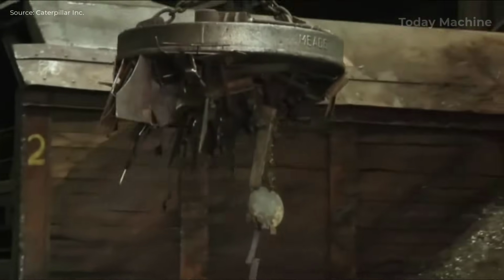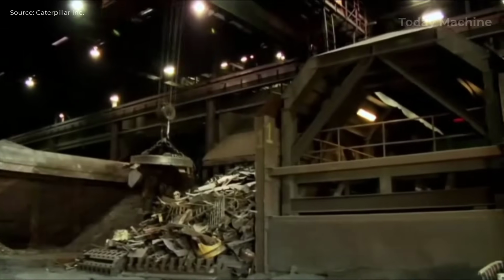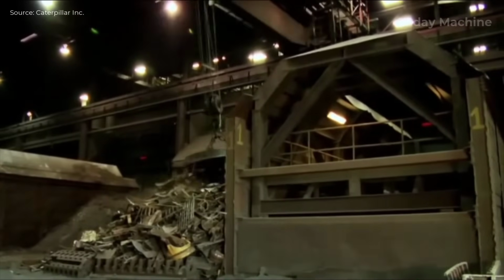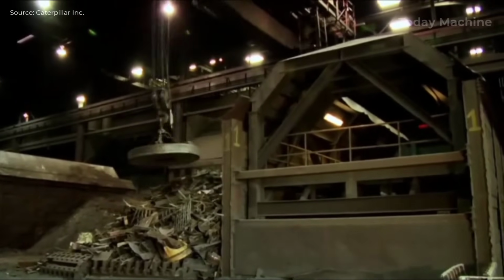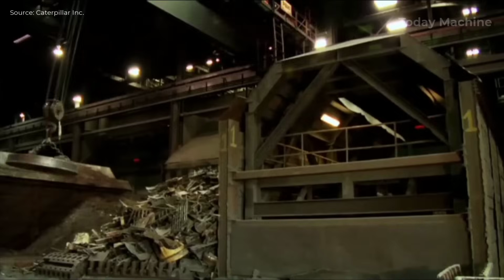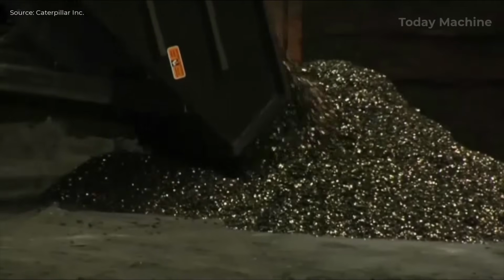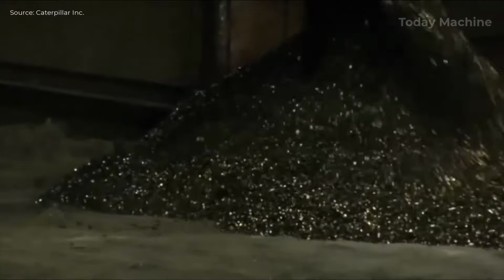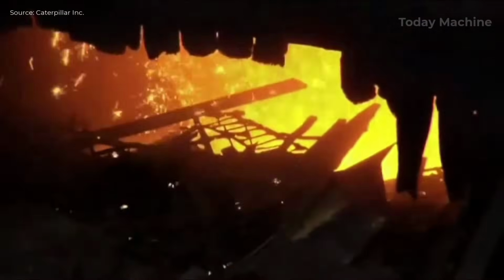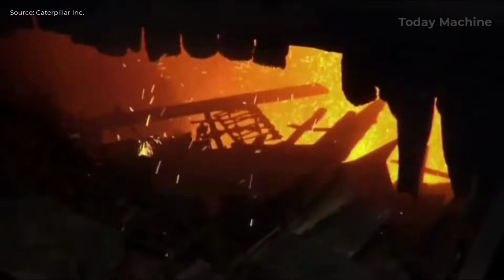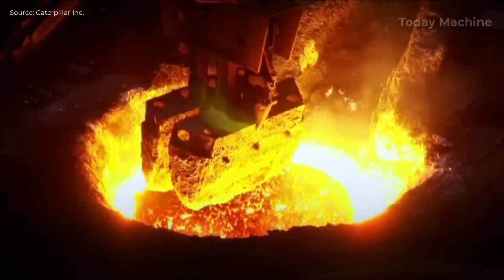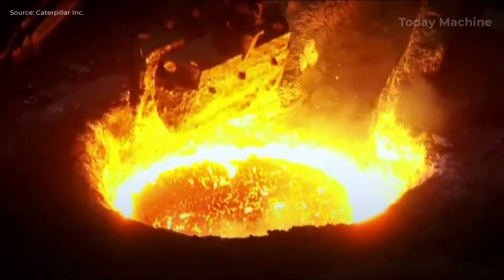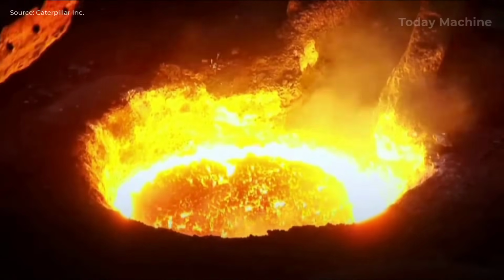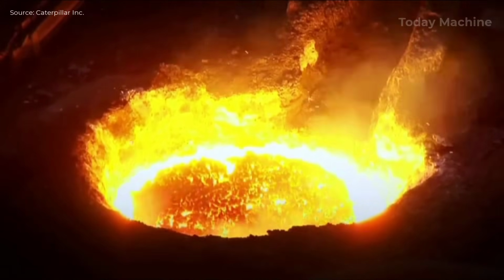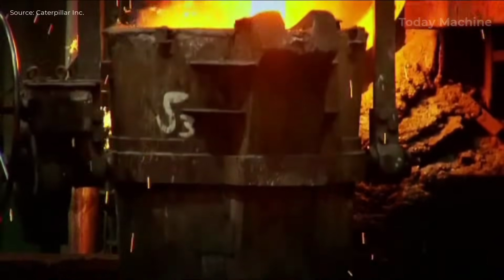The next step involves pouring molten iron into these molds. Caterpillar's Mapleton facility melts recycled steel and iron, along with added elements like carbon, silicon, and chromium, to create a high-strength gray iron mixture. This molten material, heated to approximately 2,700 degrees Fahrenheit, is carefully poured into the molds at around 2,600 degrees Fahrenheit. The pouring process is precisely timed to ensure the iron fills the mold evenly and solidifies correctly.